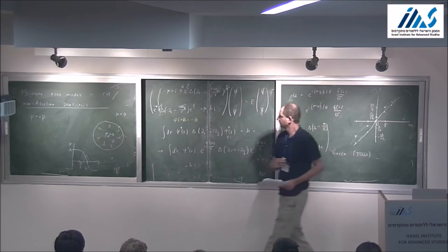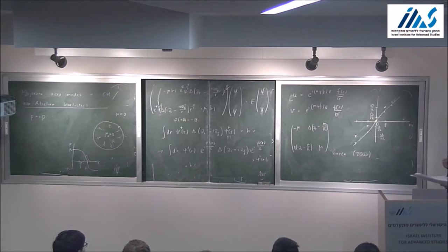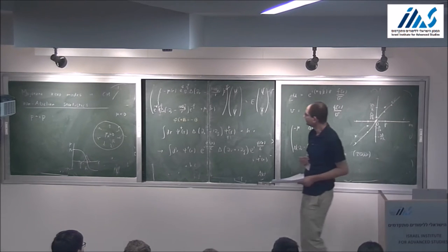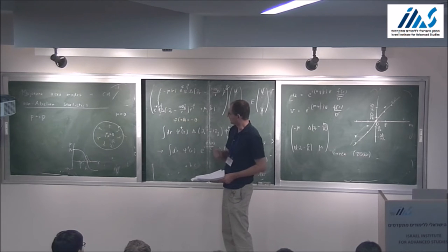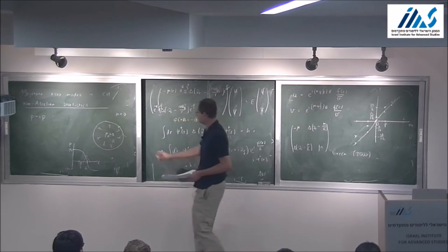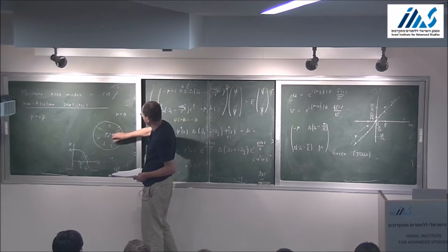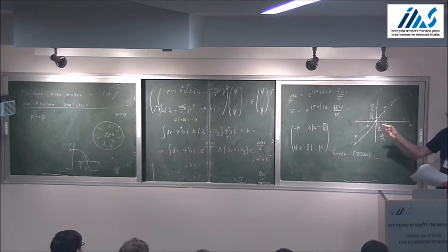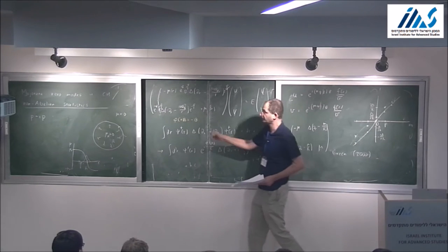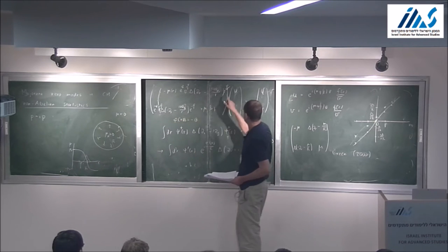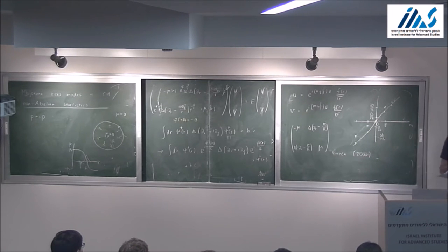Okay, it does this. And why does it shift the angular momentum by half? Well, right. So that's the part I messed up here. But morally, what it does is basically change the boundary condition, because you can basically do a gauge transformation that undoes this phase twist. But that would come at the cost of changing the boundary condition for the fermions. Roughly this is the phase of a Cooper pair, so that's twice the phase of the fermion. So if you undo the twist of this by 2 pi, there's a twist by pi of the phase of the fermionic wave function. Okay, this is the idea.